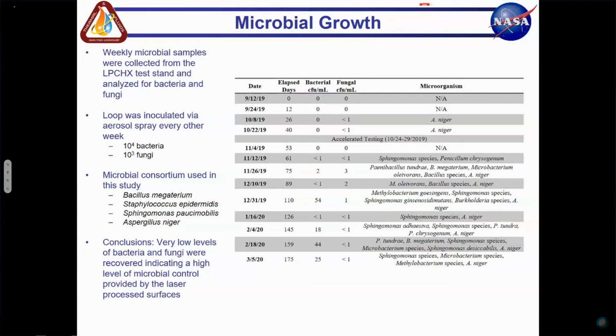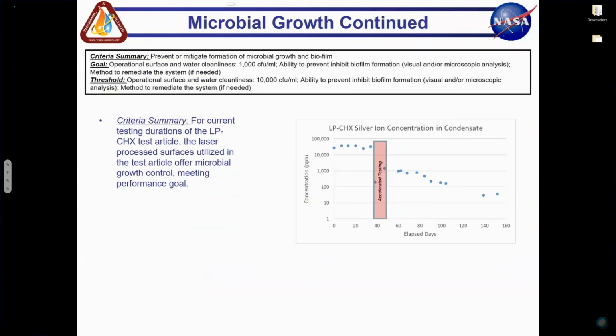And the counts that we found are on the right-hand column here. There's elapsed days, bacterial count, and the fungal count. So we're getting very low levels of bacteria and fungus recovered, which really indicates a high level of microbial control over the whole duration of testing. We did pick up a few here and there, but it was nothing at an alarming level that would cause us to take an action like a dry out.